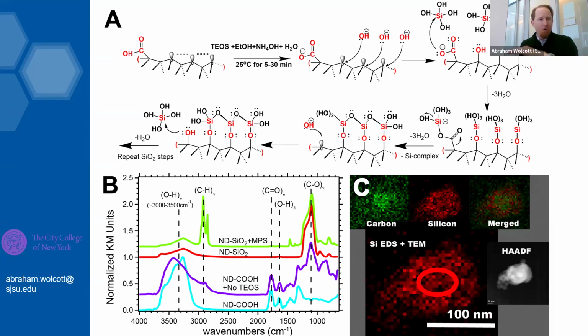So these macles are 1-1-1 terminated diamond. And I would like to see if we can just do the chemistry on the macles. Do they create this ultra thin silica coating? And then, of course, try it with the HPHT diamond, with atomist diamond, and see, does the photoluminescence change? Is it increased? Is it decreased? Do the T2 and T1 times become perturbed?